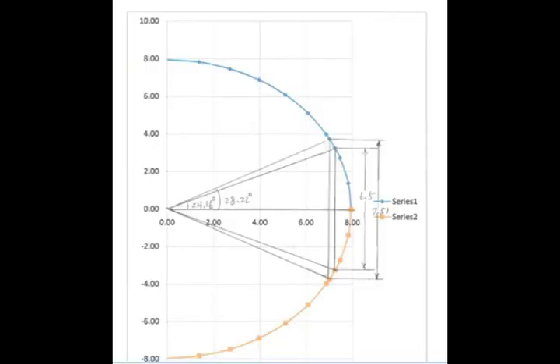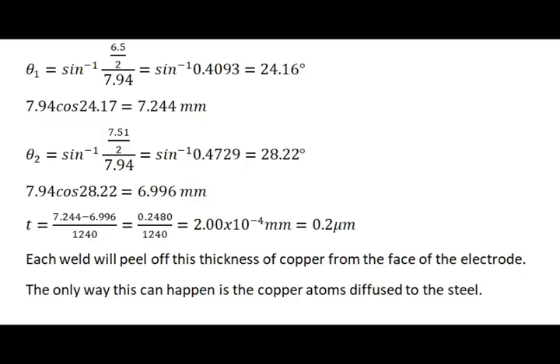Theta 1 equals arcsine of 6.5 divided by 2, then divided by 7.94, equals 24.16 degrees. x1, the distance from the center of the sphere to the 6.5 mm surface, equals 7.94 times cosine 24.17 degrees, equals 7.244 mm. Theta 2 equals arcsine of 7.51 divided by 2, then divided by 7.94, equals 28.22 degrees. x2 equals 7.94 times cosine 28.22 degrees, equals 6.996 millimeters.